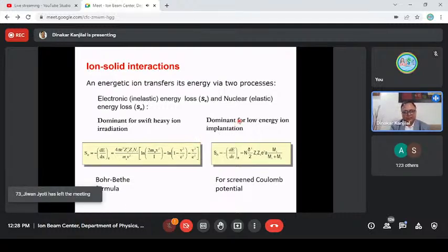And if it moves much slower than the electron, it is a semi-classical process. The electron makes many rotations compared to the time the ion takes to move around, so it neutralizes it and the electron doesn't get affected. So it goes as an elastic process. If it hits by chance in the impact parameter, the atoms get displaced. Then this happens due to nuclear energy.